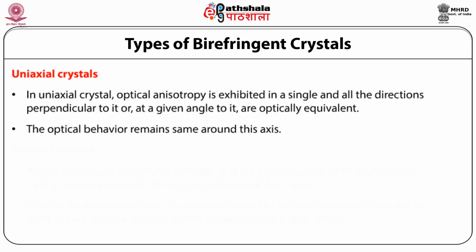However, for most of the other polarization directions, the light will be partly in the direction of the optic axis and is referred to as the extraordinary ray. The ordinary ray will always experience a refractive index of n0, whereas the refractive index of the extraordinary ray could be between n0 and ne, depending on the ray direction as described by the index ellipsoid.